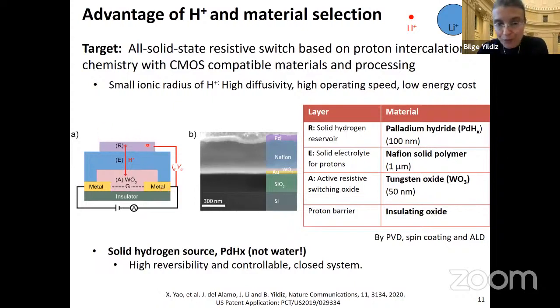And this reservoir for hydrogen can be a solid material, such as a metal hydride, and we have taken it to be palladium hydride to start with. Okay, so palladium hydride as our hydrogen source, and the resistive switching oxide we have taken to be tungsten oxide, which we know we can insert protons, at least from liquid electrochemical studies. And the separation layer, the solid electrolyte, as the fastest proton conducting electrolyte, that is Nafion. And the device cross-section is shown here, which we have fabricated by thin film deposition of the tungsten oxide, of the palladium, and spin coating of the Nafion in between.